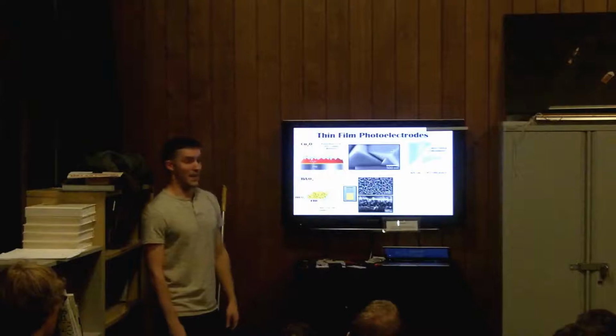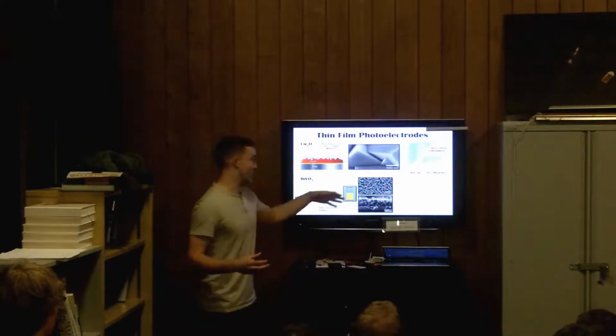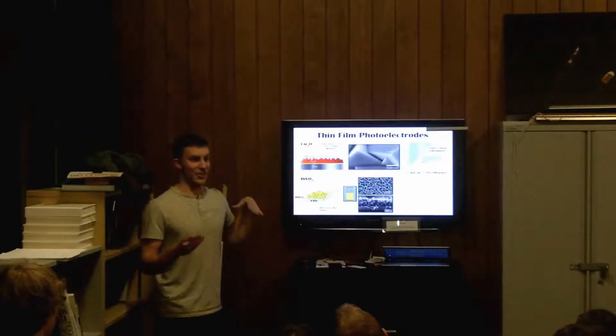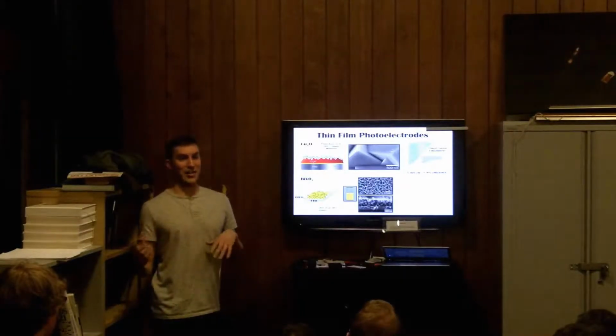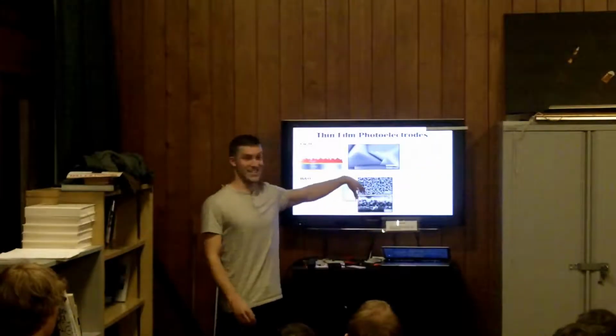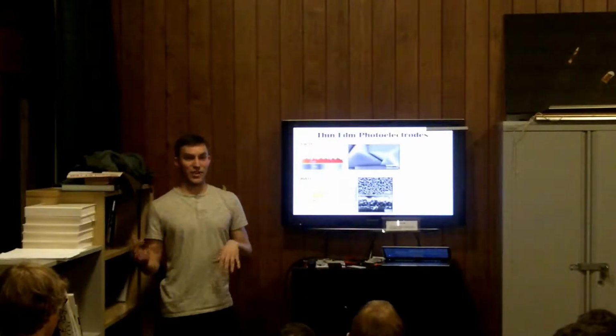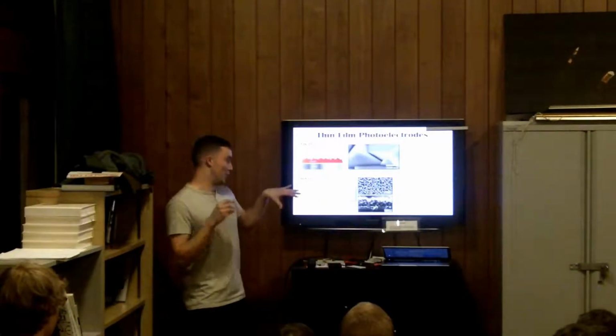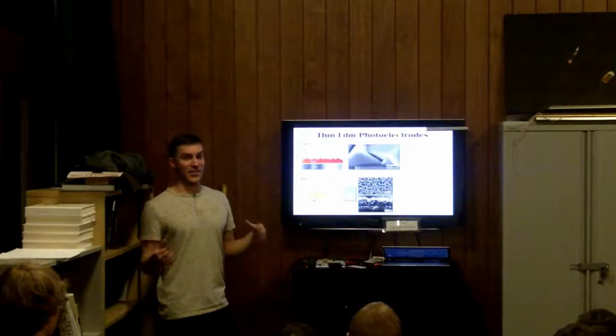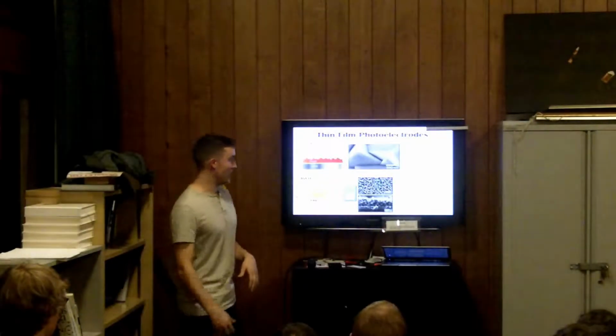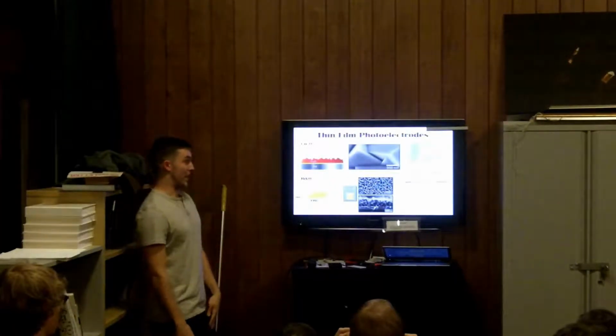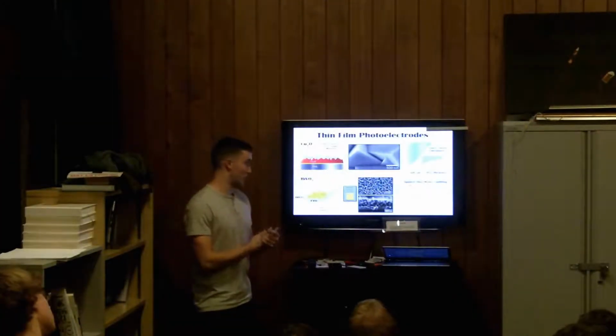Another set of SEM images just showing that there's nanostructure to these materials that actually helps induce the various reactions to occur, because you have all of these sites at which the water oxidation reaction can occur. So the morphology, or the shape that it takes on at the nanoscale, is actually very important for the results that you get. This is another way of presenting results in the field of solar fuels.